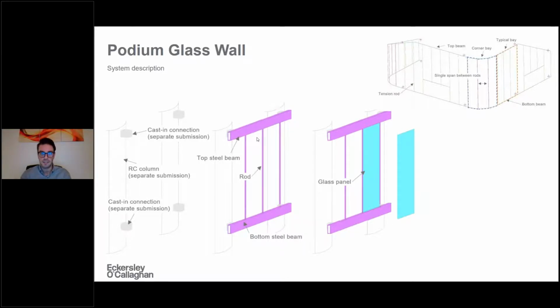While the glass is sitting on the bottom steel beam, so the dead load of the glass is entirely taken by the bottom beam, and it is clearly restrained laterally for out-of-plane loads and connected to the rods on the two vertical edges and to the top and bottom steel beam on the short horizontal edges.